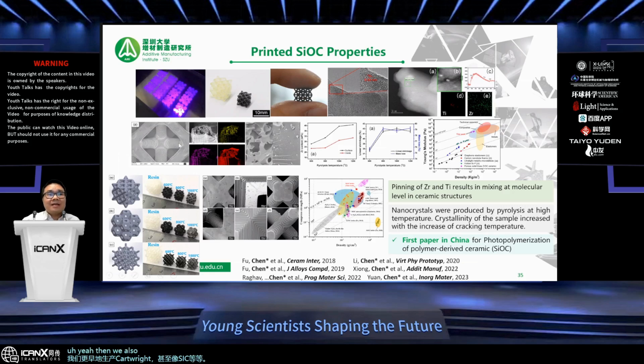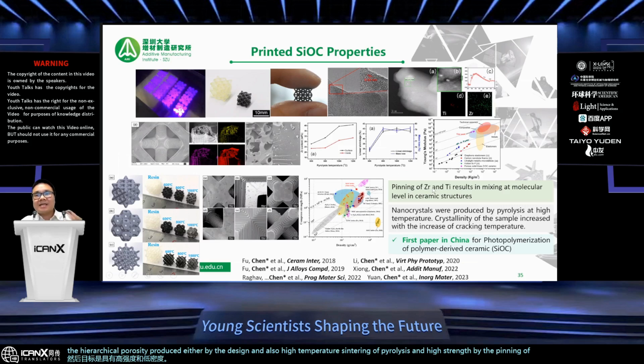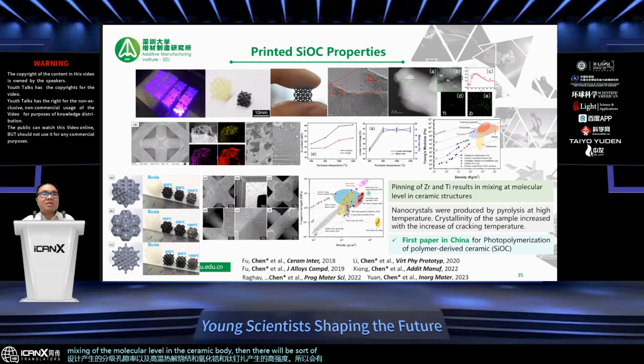Yeah, then we can also design our own hierarchical porosity, starting from the CAD model, from the design, and also from the high temperature treatment as well. You can get hollow structures inside this kind of structure. The aim is to have high strength and low density. Low density is realized by the hierarchical porosity produced either by the design or by high temperature sintering or pyrolysis, and high strength by the pinning of zirconia and titanium. So there will be mixing at the molecular level in the ceramic body. Then there will be enhancement in terms of mechanical properties.